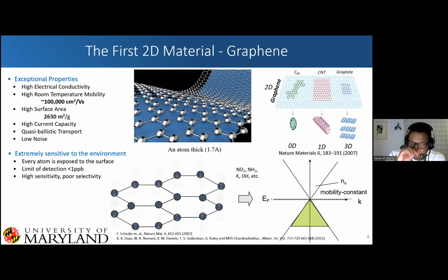And so, here we have graphene, really the first two-dimensional material, with really exceptional properties: high electrical conductivity, high room temperature mobility, high surface area, quasi-ballistic transport of carriers, high current capacity, and very low noise. And that really is to our benefit, as I'll show in some of the applications we've done. It is extremely sensitive to the environment. So every atom is exposed to the surface. We get less than 1 part per billion limit of detection, high sensitivity, but very poor selectivity.